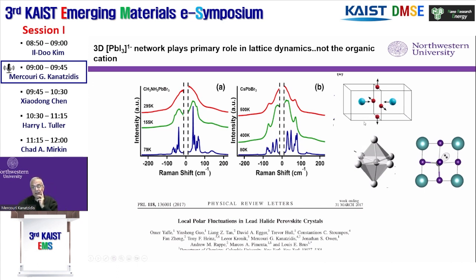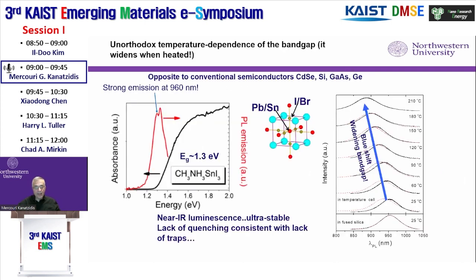So that arrangement makes everything dynamic, and therefore, when you excite electrons across the band gap with illumination, this dynamicity causes the electrons and holes to get lost for a while before they can find each other and recombine. Because the lattice has changed. By the time they get to the excited state, the lattice has changed. And so it takes a while to recombine, and that lengthens the lifetime of the photoexcited carriers.